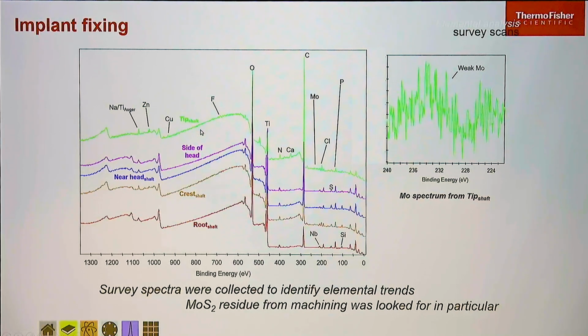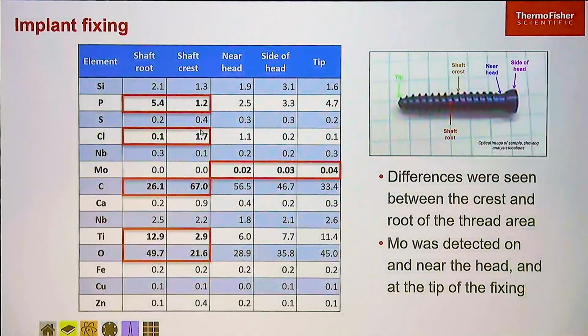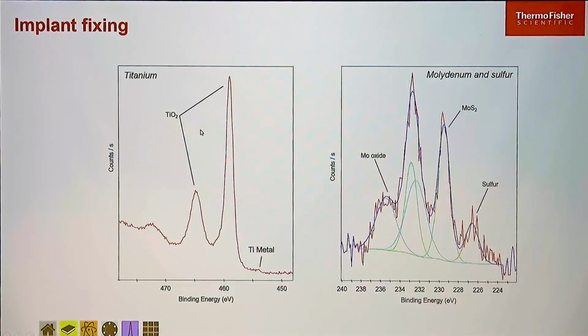And we can see various different elements present. Now, it's supposed to be titanium, and nearly everything else that is there shouldn't be there, basically. Well, actually, the copper and the zinc is supposed to be there. Molybdenum isn't. Carbon, obviously, is a ubiquitous contaminant, so we'll see that pretty much everywhere. And from those survey spectra, again, we can do what we've done every step so far, and we can do quantification. And so the important ones where we want to look, we're seeing differences between the crest and the root. So we want to investigate those a little bit further and see what's causing these differences in composition. And near the head, we're also seeing some evidence of molybdenum being present and some sulfur, and understand those as well.